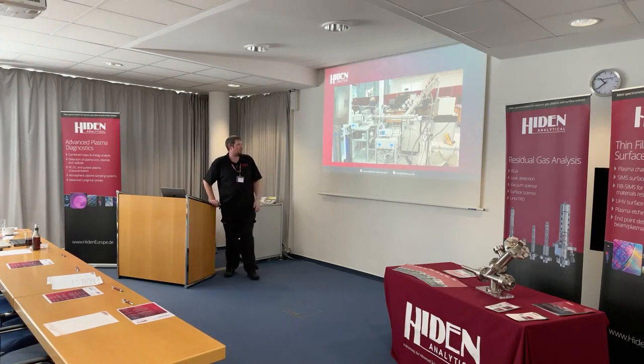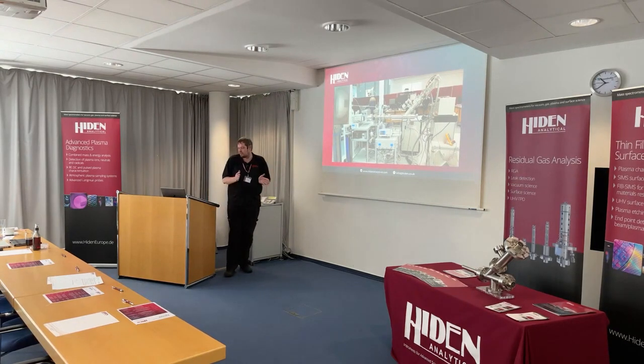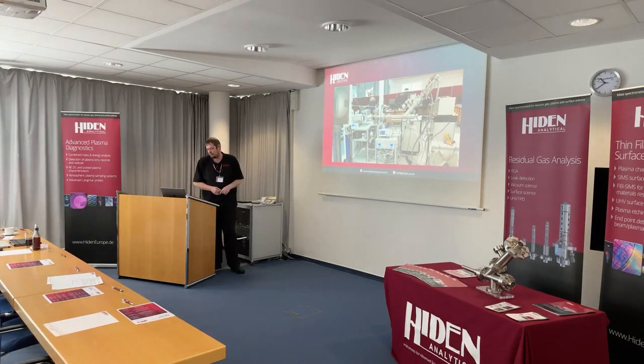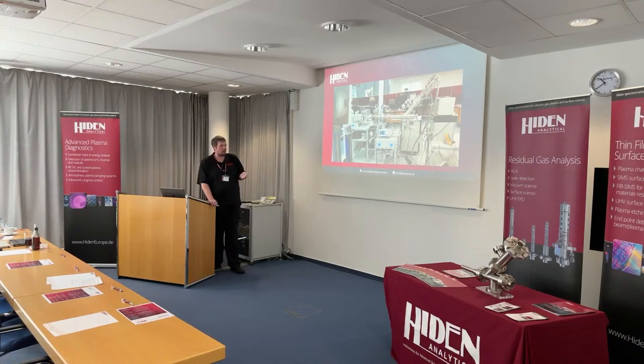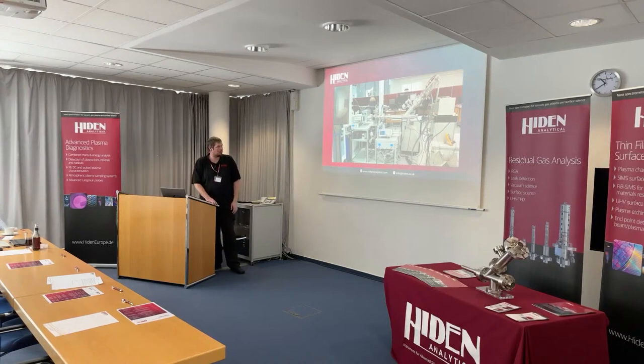So it's a capacitively coupled plasma. The view through the window, you can see in the top corner. So the electrode's on the left, the EQP is on the right. Typically keep it about 5 to 10 centimeters away. So 13.56 megahertz plasma, so we have the matching network. And we can also pulse the plasma using the function generator, so we can do time resolved studies as well.